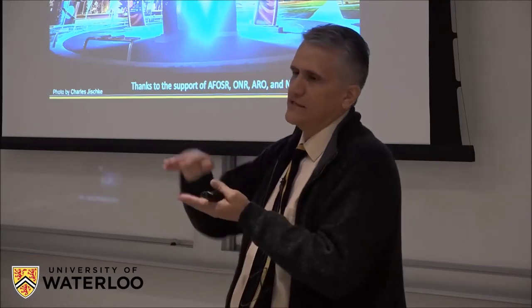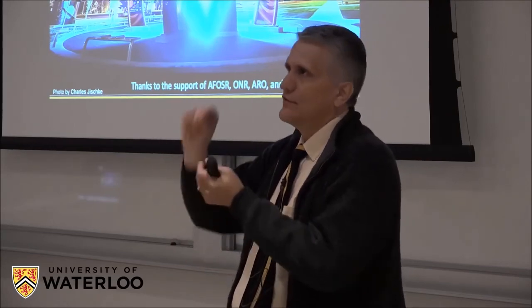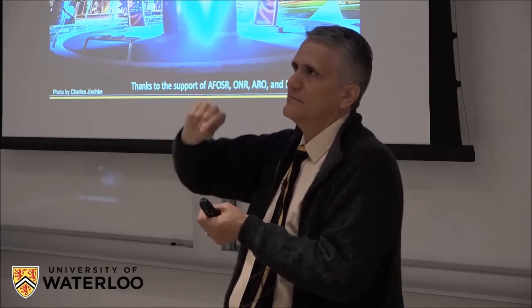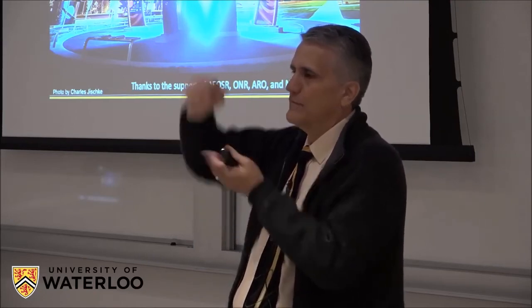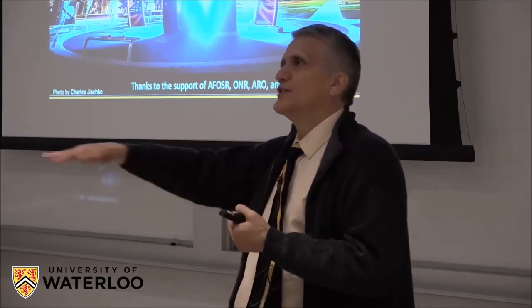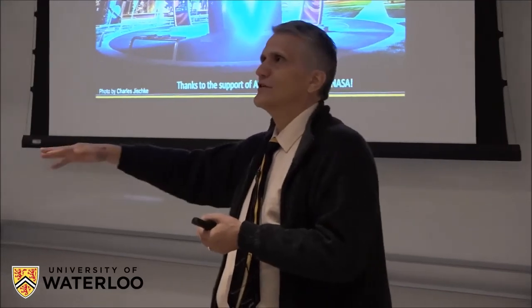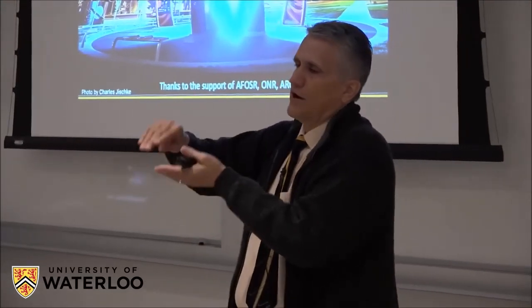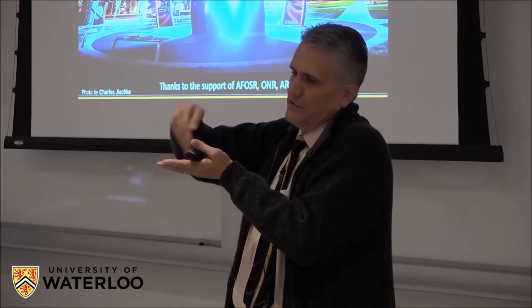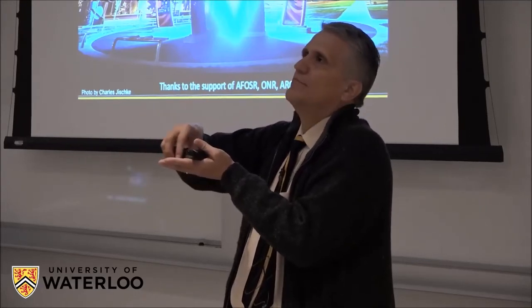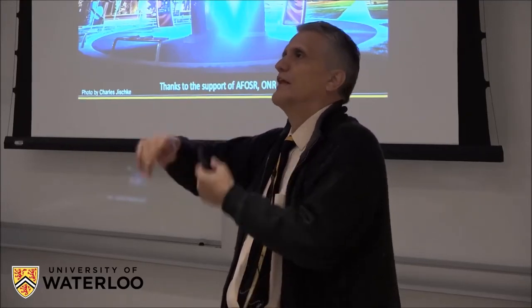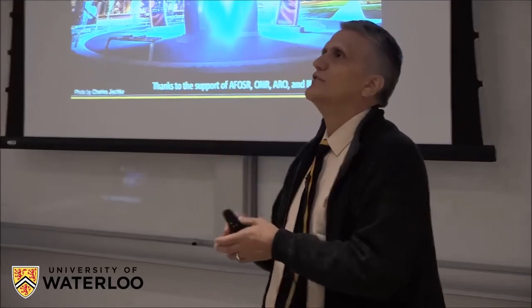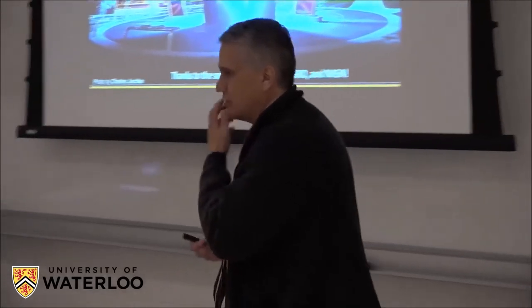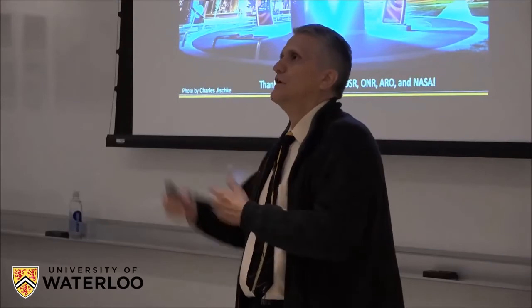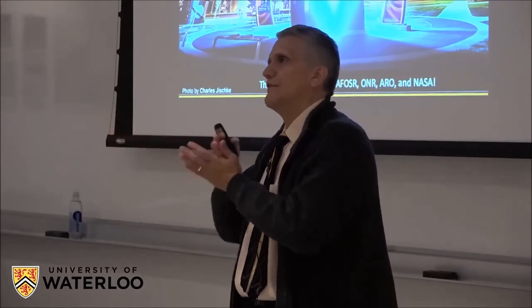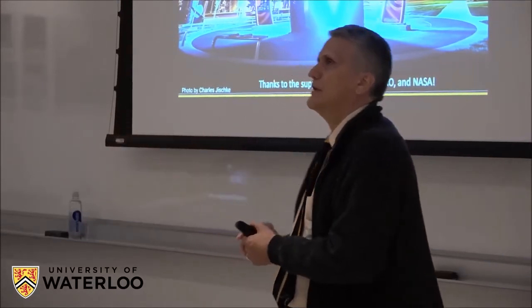As those are deposited, as you go thinner and thinner, the interlayer space, right? You make thinner foil materials, and the propagation speed will go faster and faster. But you get to a point where, even as you deposit the layers, a little bit of partial reaction occurs, and it'll start to slow down, and you'll have partially reacted the material. So there's often, in general, an optimization of the layer thickness and so forth.